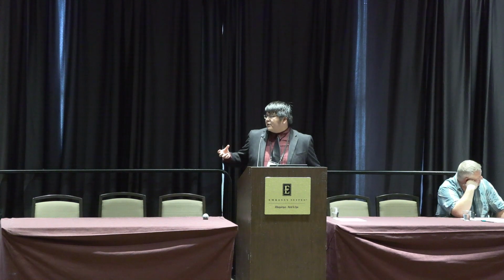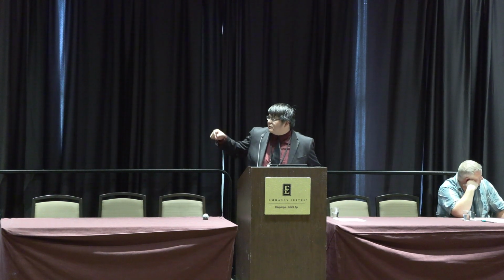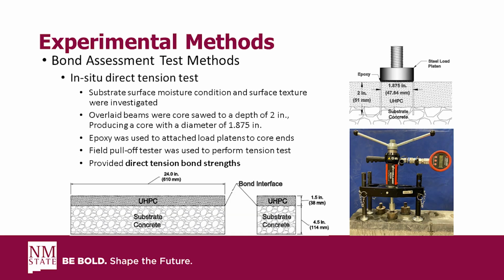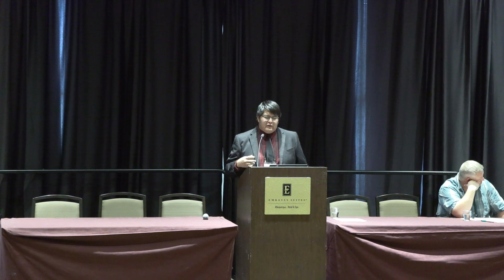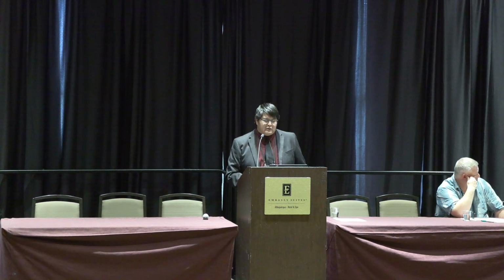And all we do is epoxy on a steel load platen, as you see in the top right illustration, and then you can see them down there in the bottom right photograph. We just epoxy that load platen on there, allow it to cure, and then use this pull-off tester to perform the direct tension pull-off test. And of course, this does provide a direct tension bond strength.